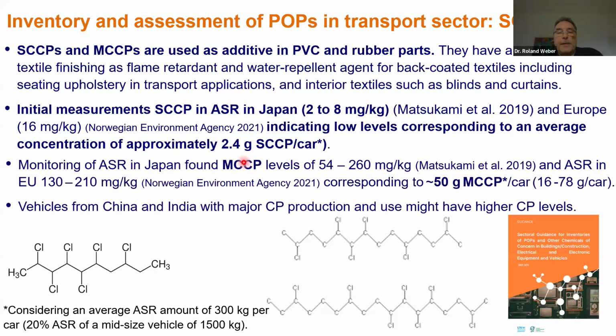Also, the MCCPs, which will be listed in 2025, have been analyzed. So the levels here are considerably higher. In Japan, it was between 54 to 260 milligrams per kilogram, and in the automotive shredder residue in Norway from European waste, it was between 130 to 210. Also here you see the data are quite robust, very comparable. So therefore we have proposed here for SCCP 2.4 gram SCCP and 50 gram MCCP per car.